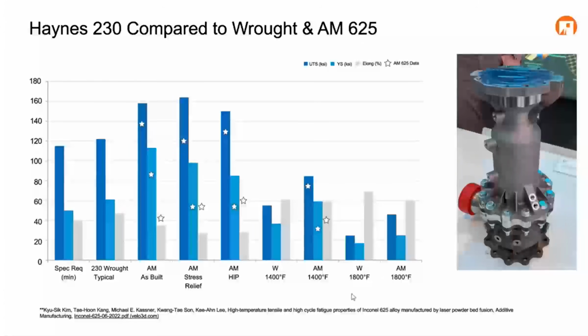But what has us really excited about this is we retain those benefits in our strength as well as elongation all the way out to 1800 degrees Fahrenheit. You can see the comparison between the wrought and additive manufactured version at 1400 here and 1800 there on the far right hand side. Again, still remaining highly ductile, but we're getting these increases in strength over the wrought alloy.